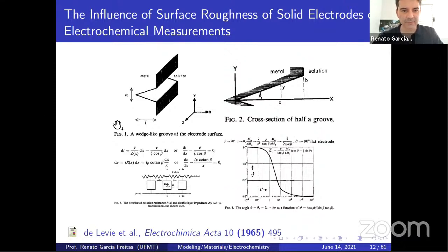So we have here, de Levie suggests a V groove. A V groove is an imperfection which we consider further as a pore. So a V groove is a pore like this one, if the pore is under the Z axis. So if you have the pore condition under the Z axis down there, we have a two-dimensional problem to solve. So we can make this model quite simple, into a one-dimensional model, resulting in only this half of this V groove down here, if we change the size of half the groove.